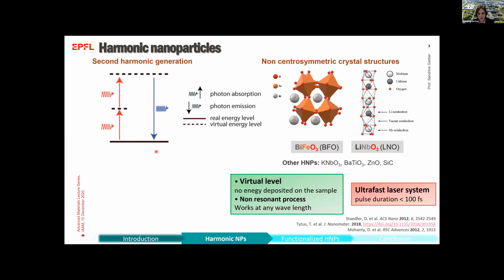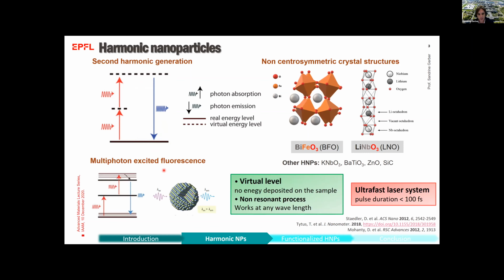So in this respect, they differ from upconversion nanoparticles, represented here, where in fact they absorb two photons, and these photons add their frequencies to match the difference between two molecular levels. So in the harmonic generation process, there is no energy which is deposited on the sample, because you only reach a virtual level. On top of that, the process can be generated at any incoming wavelength generated by an ultra-fast laser pulsed system.